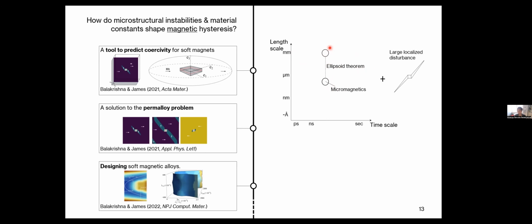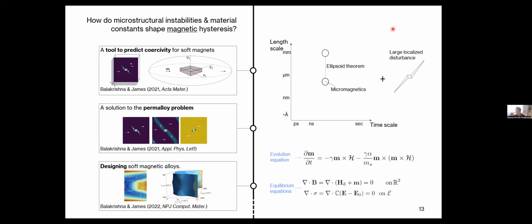And then to this model, we are introducing a localized disturbance, which we model by a simple example of a needle domain or a spike domain. And we compute our evolution by using the Landau-Lifshitz-Gilbert equation. And we compute equilibrium conditions wherein we compute the magnetostatic fields or the demagnetization fields, and we ensure this stress is equilibrated at every time step.